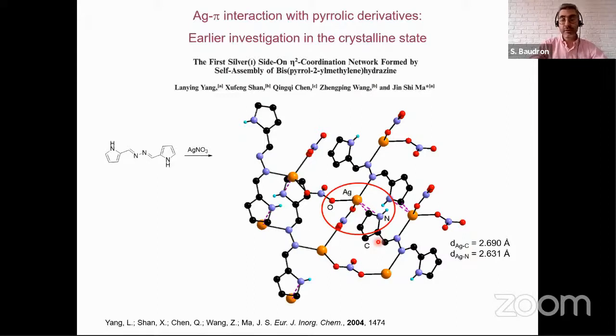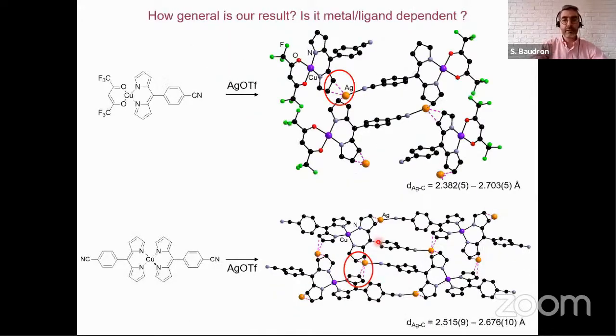So we went on to study our complexes and investigate their assembly with silver 1 cation. Domingo Salazar, who was a PhD student at the time, obtained results here with heteroleptic copper complexes or homoleptic copper complexes. In both cases, he obtained a rather complex set of coordination polymers, where once again the silver is coordinated to the peripheral nitrile, as we had anticipated, but also interacts with a carbon-carbon system of the pyrrolic skeleton of a dipyrrin, either in a combination of eta 2, eta 1, or with two eta 2 systems. As you can see, this is rather versatile depending on the type of organization. So it seems that this can be observed indeed with the zinc tetrahedral complex, but also with copper square planar or pseudo-tetrahedral complexes too.